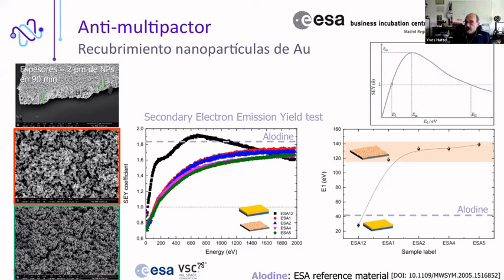If you are able to move the energy to high energies, you will have a larger safe region for your device. And what we have shown is that with our coatings, the E1 energy that is represented here is more than 100 electron volts, which is much more than the standard coating called Alodine, which is around 40 electron volts. So we are quite confident that our coatings made of gold nanoparticles can reduce significantly the probability of a breakdown voltage and the cascade of electrons inside the devices.